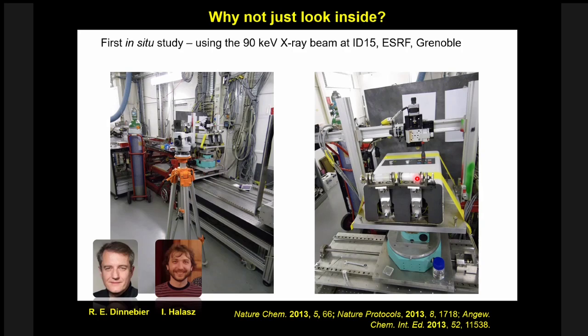So one problem with this method is sometimes the sample gets sticky and gets stuck to the actual milling jar. And you see your signal slowly being lost, and then you say, "Oh my God, I'm milling my material until it loses crystallinity. It's becoming amorphous," and it's not really what it's doing. It's just simply getting stuck to the walls and not being exposed to the beam. Okay. All right. That makes sense.